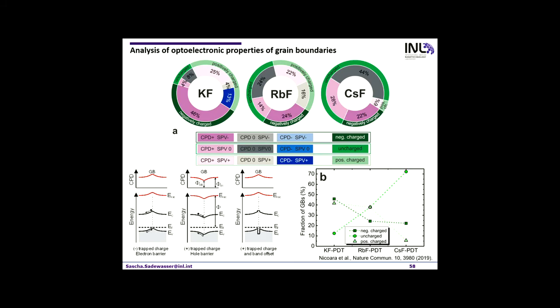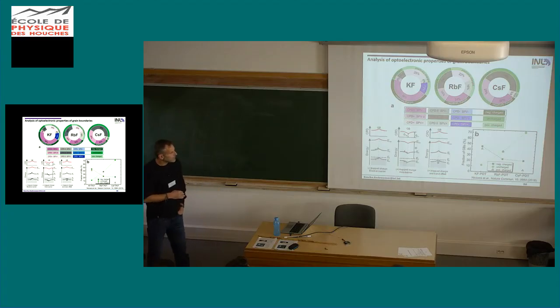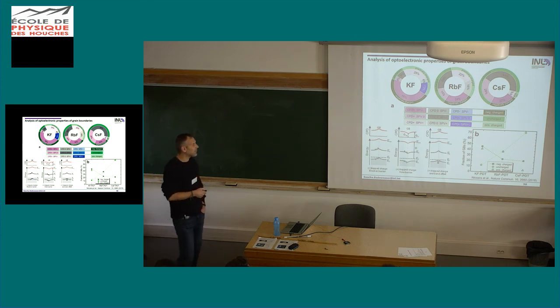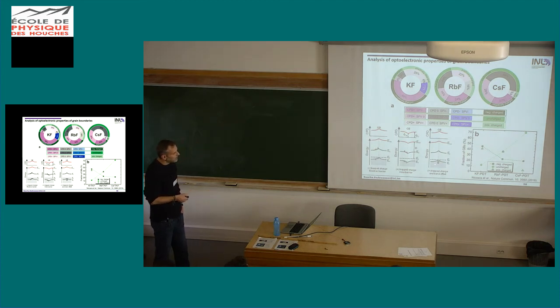So we try to go one step further, and we come back now to the surface photovoltage. We also illuminated and studied the grain boundaries again. Essentially, we have cases where we have a higher work function at the grain boundary, and a lower work function at the grain boundary. This can be due to band bending, but this could also be due to a different material. I mentioned before that the alkalis tend to sit at the grain boundaries, so there might be some alkali phase formed at the grain boundaries. So we might also have a different phase at the grain boundary.